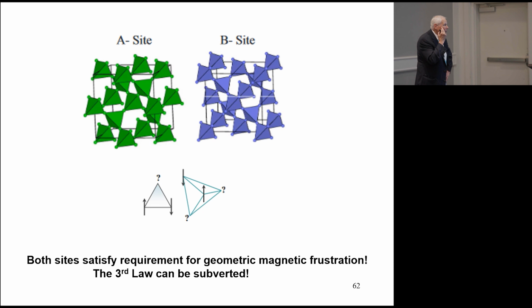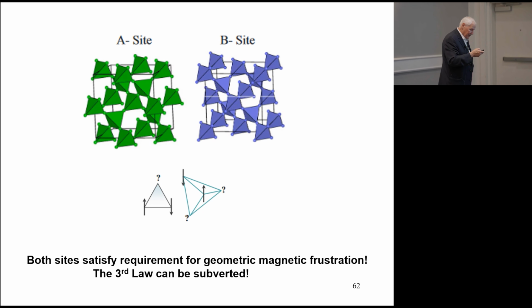The most useful thing about pyrochlores, both the 16d and 16c sites are occupied, so they share something with spinels, in which only one of those sites is occupied. And as it turns out, for both sites, if you look only at the metal site positions, they form perfect three-dimensional arrays of corner-shared tetrahedra. And of course, this is the ideal environment for geometric magnetic frustration. Here's a triangle, and here things get even worse with the tetrahedron. It's impossible to satisfy all of the antiferromagnetic constraints on the corners of a tetrahedron. So, as it turns out, you can use this sort of stoichiometric situation to subvert the third law of thermodynamics, right?